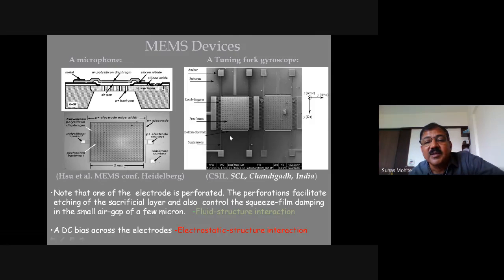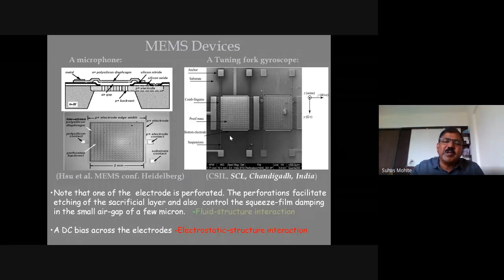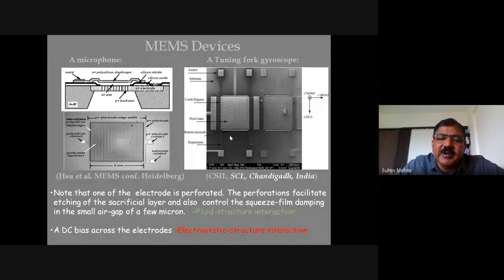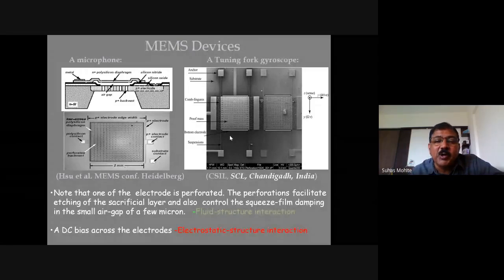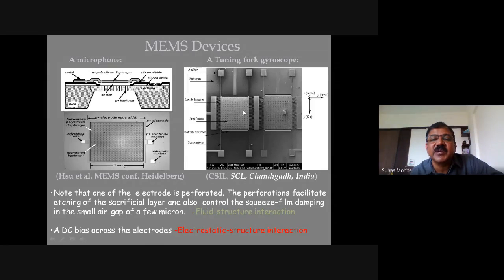The gap between this plate and the substrate is 2 microns, 3 microns or 4 microns, which is a very, very small fraction of that of a hair. And therefore, to be able to get a freestanding structure, a structure which is separate from the substrate, which is hanging from the substrate on these anchors.